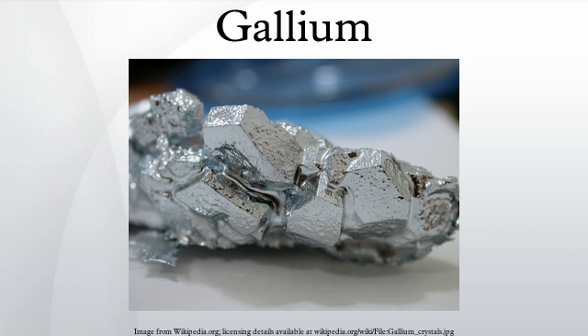A mercury cell electrolysis and hydrolysis of the amalgam with sodium hydroxide leads to sodium gallate. Electrolysis then gives gallium metal. For semiconductor use, further purification is carried out using zone melting, or else single crystal extraction from a melt. Purities of 99.9999% are routinely achieved and commercially widely available.